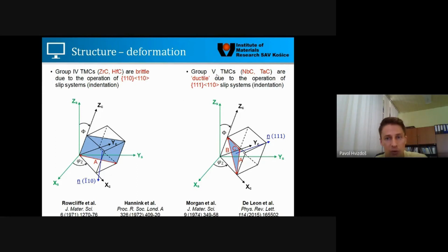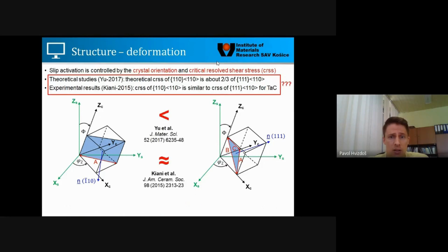Group 5 transition metal carbides, which comprise niobium and tantalum carbide in our case, can deform in a ductile form, where the slip plane is the 111 instead of the 110. The slip direction is exactly the same. This is due to the fact that group 5 transition metal carbides have an extra valence electron, which gives them a bit more metallic character. Theoretical studies showed that the critical resolved shear stress for the slip on the left side, the 110 plane, is lower compared to the 111.